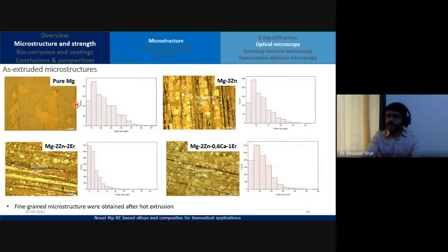Whereas once we extrude these materials, what we see here is that the grain size becomes fine-grained. You could see here certain black marks. These are the secondary phases that have got deformed along the extrusion direction. You see here the extrusion direction is vertical, and here the extrusion direction is horizontal. For this particular alloy, we could see some sort of a bimodal distribution. So you have certain coarse grains, certain undeformed grains, and then certain fine grains as well. We are going to look at that in the EBSD.